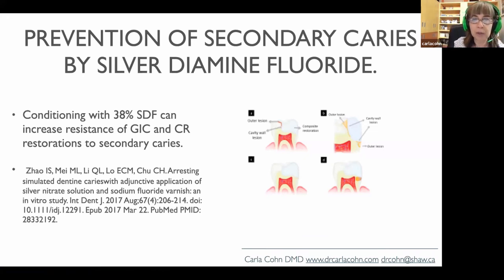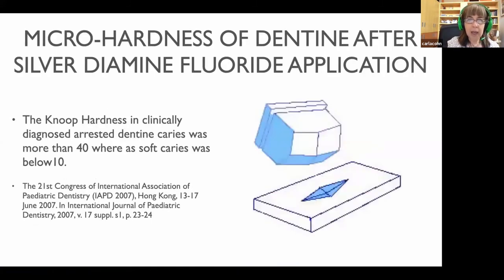caries: conditioned with 38% silver diamine fluoride can increase the resistance of glass ionomer and composite resin restorations to secondary caries. And micro hardness of the dentin after silver diamine fluoride application. So that Knoop hardness in clinically arrested dentin caries was more than 40, whereas in soft caries was below 10. So that's very significant. Let me see if I can give you that study one more time.